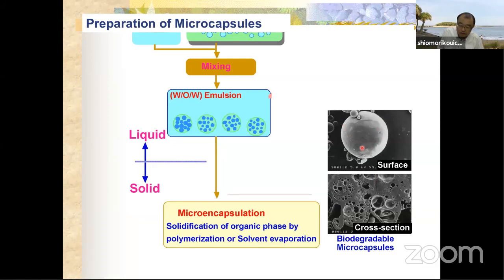The surface is very smooth, and on the inner side there are many spherical pore-like structures. These pores are traces of the inner aqueous phase droplets. Before the SEM image observation, we dry in vacuum as a pre-treatment, evaporating the organic solvent and aqueous solution. Water is removed from the particles.